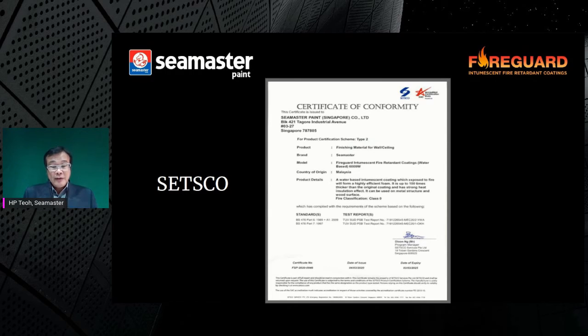Seamaster fire retardant protection is one of the easiest, oldest, and most efficient ways to protect materials against fire. This approach does not cause chemical modification of the substrate, but rather the formation of a protective layer, which alters the heat flux to the substrate and can inhibit its thermal degradation, ignition, or combustion. The ideal coating should have minimum flame spread, negligible or low release of smoke and toxic gases, be easy to apply, show good weather resistance, adhere to the underlying substrate, and offer low cost.